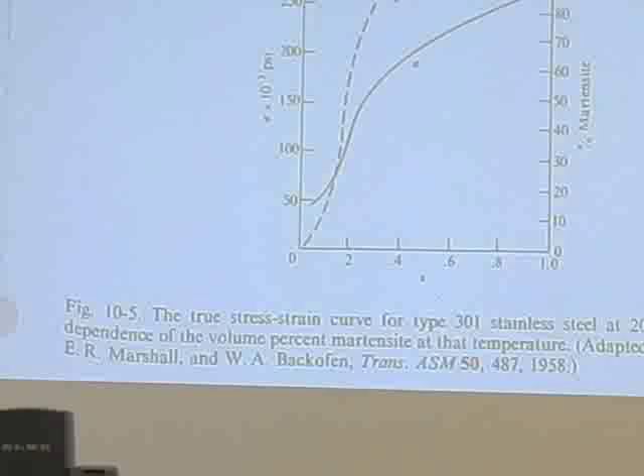And in fact, today, this is the latest thing in the last couple of years in automotive steels, is to develop steels that are TRIP steels, transformation induced plasticity, so you can get deeper draws with a single set of dies. It's an alternative, if you will, to superplasticity. It's not as dramatic as superplasticity, but it can eliminate half your dies in some drawing operation. Or you can successfully make a draw that otherwise wouldn't work.